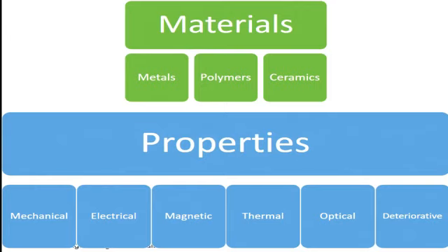And it has drastically different properties, to the point where, with catalytic converters, if you use platinum, another metal, bulk platinum wouldn't have the same effect as nanostructured platinum. Your catalytic converters in your cars use nanostructured platinum, and even though you have a nanometer or 2 of platinum, it reacts way better and is way more efficient at converting CO to CO2 so that your car meets emission standards than if you use bulk platinum. So yes, platinum is a metal, but nanostructured platinum is different.